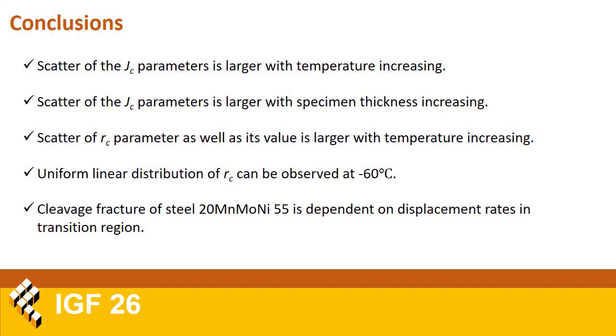A few observations could be emphasized. The scatter of JC parameters is larger with temperature increasing, which can be seen from direct comparison of JC values. The scatter of JC is larger with specimen thickness increasing, but it has not been seen from the results of testing of CT50 specimens with B net of 16 and 20 millimeters. The only thing that could be said is that the thicker specimen gave more conservative results, but yet scatter is also large in a very broad range.